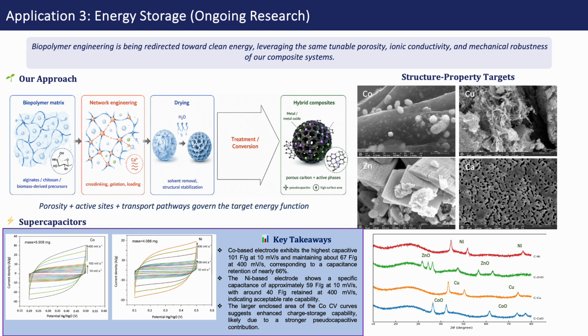Porosity improves electrolyte accessibility, while the presence of metallic or metal oxide nanoparticles can introduce additional pseudo-capacitive contributions. At the same time, the carbon framework supports electronic conductivity and charge transport. The electrochemical response is evaluated through cyclic voltammetry, so the larger enclosed area of the CV curves indicates enhanced charge storage capability. Among the tested systems, the cobalt-based electrode shows the highest capacitive response with about 101 farads per gram